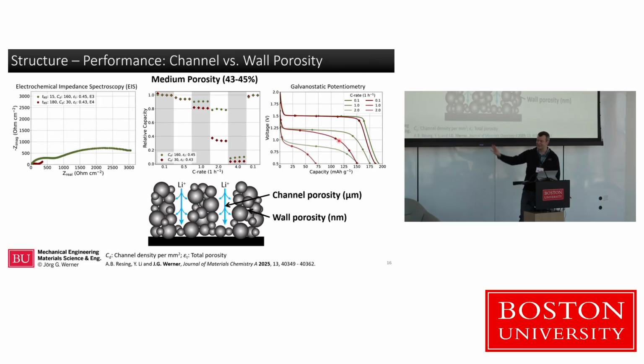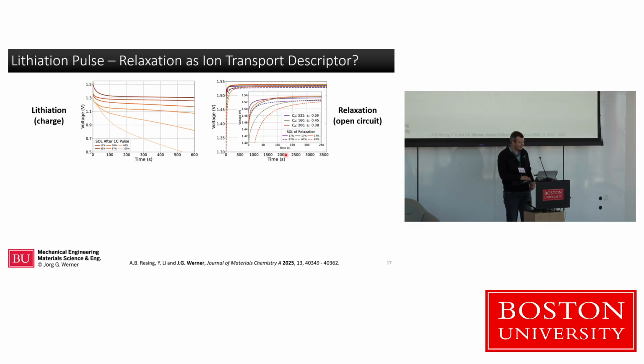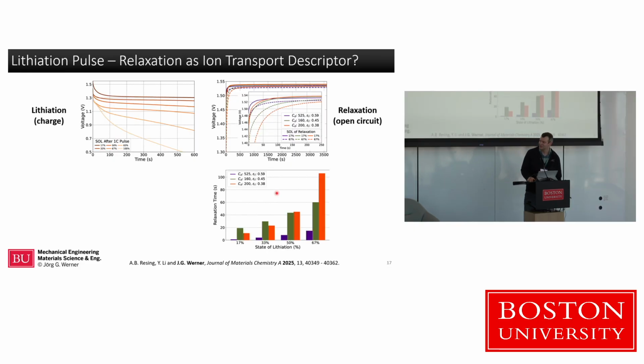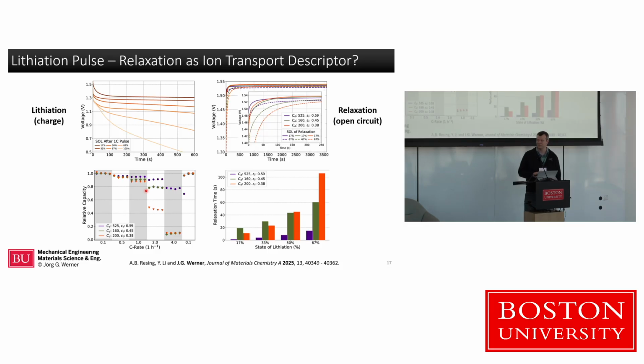So there's a lot hidden in this data here that we often don't look at because this is kind of our standard performance data, which really just gives us the endpoint, right? But between these kind of things, we can ask, well, what is actually the data that matters? What is the one we should, for example, import into an AI model? What's the data that we should simulate if we couple experiments with simulation to get bigger data sets, right? So these are things we have to think about. We started doing some other data gathering too, in particular relaxation data, where we charge our battery at a high rate for just 10 minutes or so, and then we watch the voltage at open circuit relax back to its thermodynamic equilibrium. And how fast that happens seems to correlate really nicely with exactly how well they perform, right?